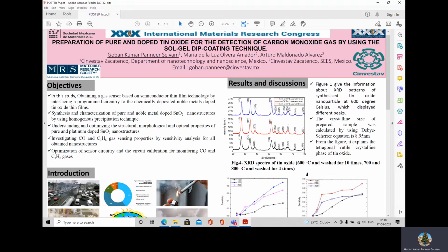The crystalline size was calculated by using the Debye-Scherrer equation, and the crystalline size is 8.95 nanometer. It also explains the tetragonal rutile crystalline phase of tin oxide.